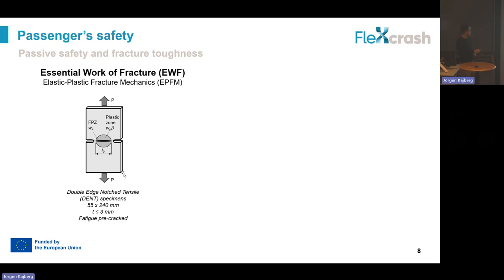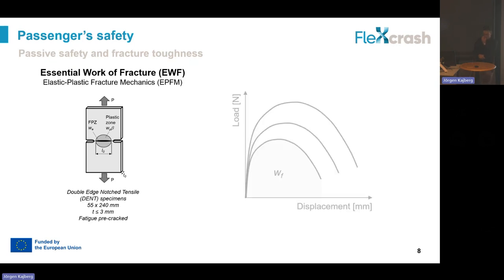So here we are using this technique, the essential work of fracture, where we are testing different DENT specimens, these double-edged notch tensile specimens, where we have a different ligament length. The ligament length is the distance between these notches with cracks, fatigue pre-cracks in the notch, and we test them until fracture.